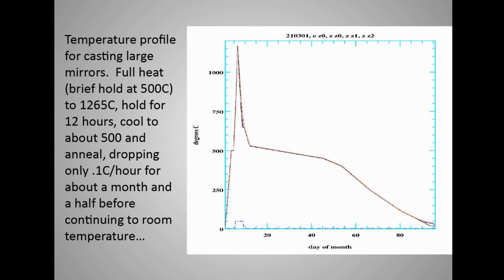Then they cool it just as rapidly, and then it's the anneal time for about a month and a half, 0.1 degrees per hour, so about 2.5 centigrade per day through the annealing process, and then a more rapid cool down to room temperature. It takes about 3 months altogether for the entire casting process once the glass is installed.